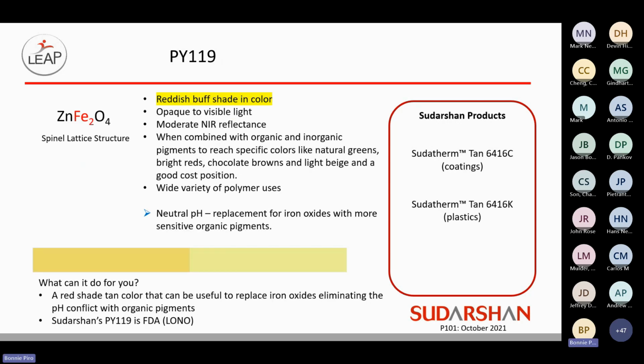Pigment Yellow 119 is the first one in the spinel structure category. This is a very nice tannish color. It is a good pigment to use with other organic pigments to be able to get some very specific color spaces like bright reds and chocolate browns, light beiges, and it offers high opacity as well as good durability. This one, like the Pigment Yellow 164 I just spoke about, has a neutral pH, so it's a good replacement for iron oxides. And our product is FDA compliant via a letter of no objection.